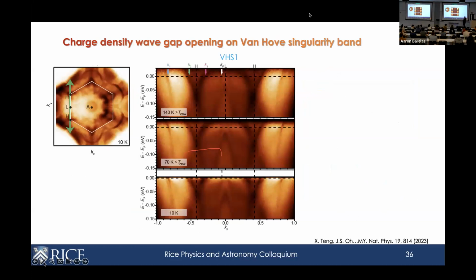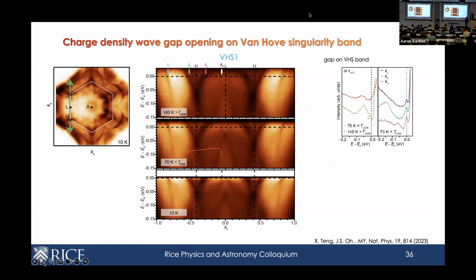endpoint. The last bit I want to show about iron germanium is that can we actually see the Van Hove singularity participating in this charge density wave order? Oh, wow, okay. And the answer is yes. So the way we can see that is the following. So imagine we take a cut here, which is shown here. We can look at the energy-dependent density of states. So here, this is this EDC or energy distribution curve. And as you go across the CDW order, this develops a